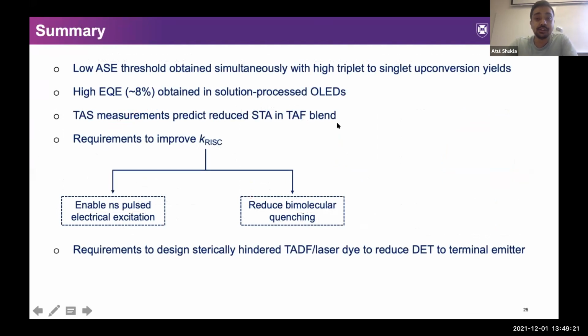So coming on to conclusions, we were able to still demonstrate low thresholds and high EQE with the TADF assisted system. And even though we were able to reduce STA, the main concern here is the quenching of triplets itself. So a higher RISC would allow us to go to the nanosecond pumping regime again, which further allows us to go for higher current densities and also reduce the bimolecular quenching processes. And lastly, to reduce the Dexter energy losses to the end emitter, we would technically want our laser dye to be sterically protected so that this Dexter energy transfer is reduced.